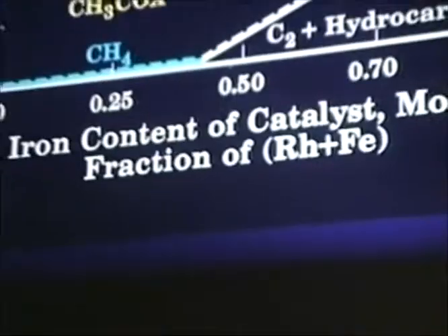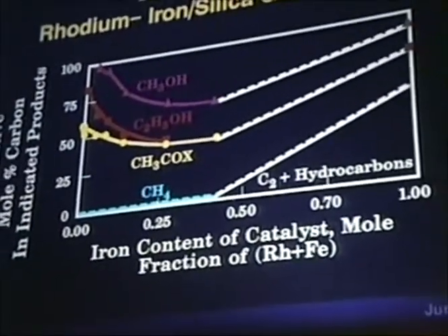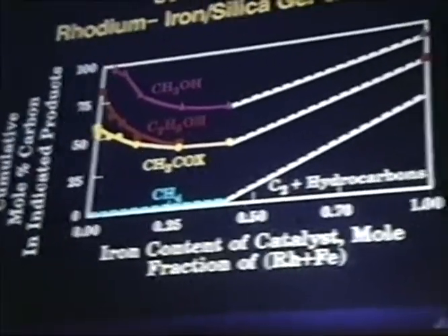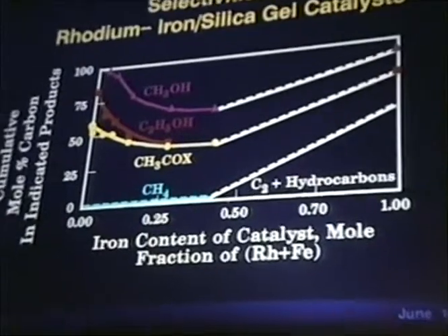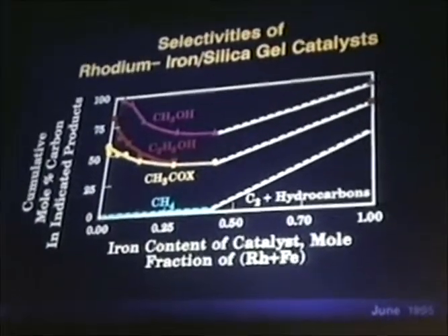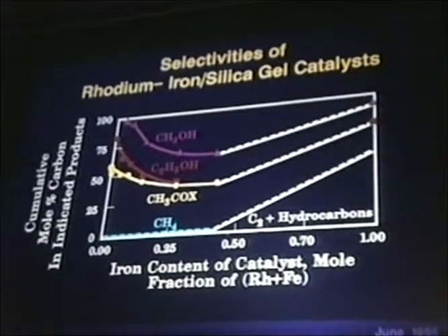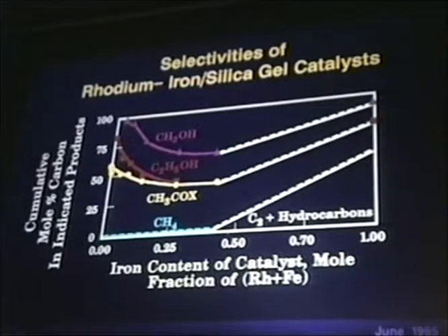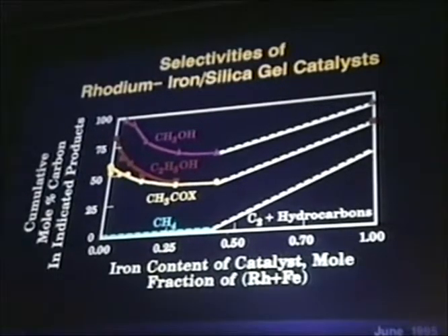As you can see, the methanol, which is the upper portion of the curve, and the area bounded by it increases, and so does ethanol. And that is coming at the loss of acetaldehyde and acetic acid. Methane is insignificant at the low fraction, but as you continue to add iron, certainly the C2 plus hydrocarbons increase.